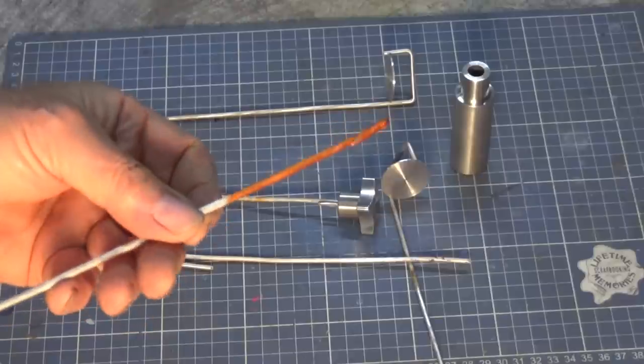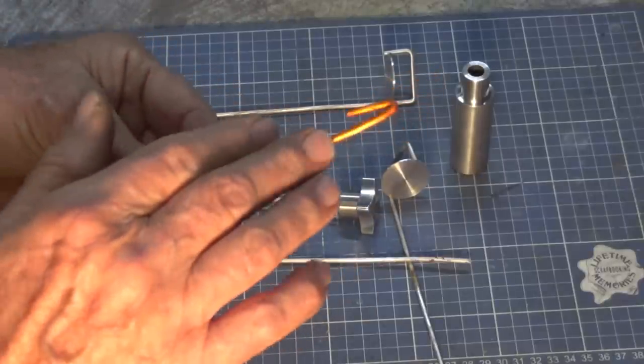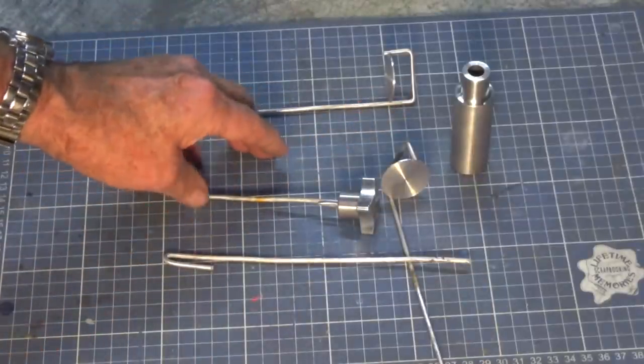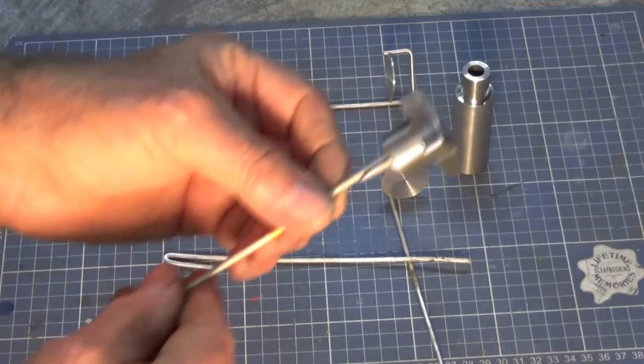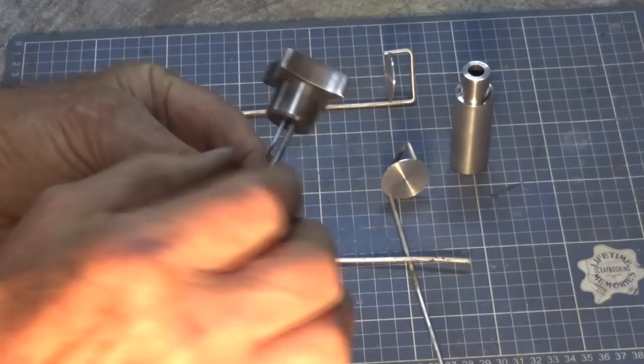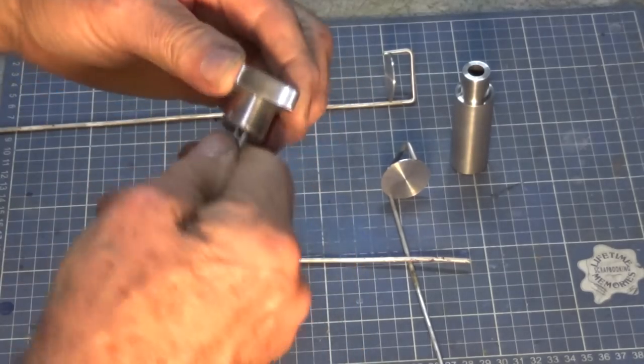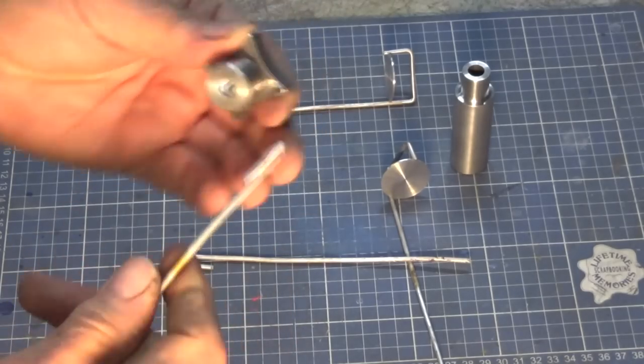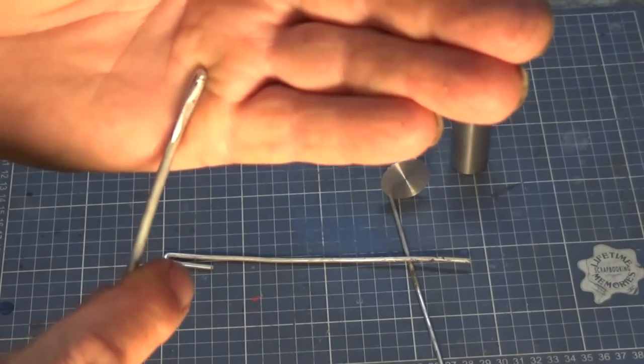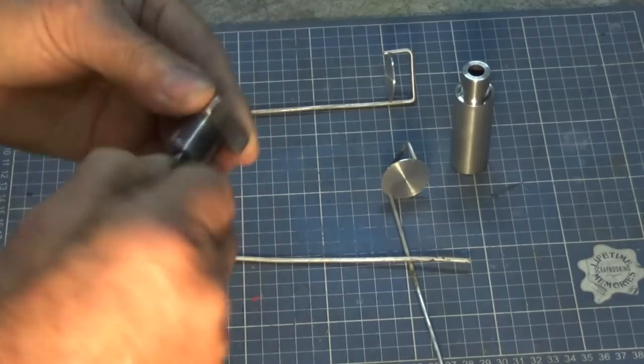Either way you've got to get rid of that old anodised coating if you're reusing the wire. With titanium wire it's more resistant to the anodising process and you can reuse the wire fairly easily. You need to get a little bit inventive about how you're going to make contact with the part. This one here has a threaded hole in the back so I've doubled the wire over and organized it so that it's a tight threaded fit into the part. That wire bites in to the threaded hole. As long as you're getting a solid electrical contact it should be good.